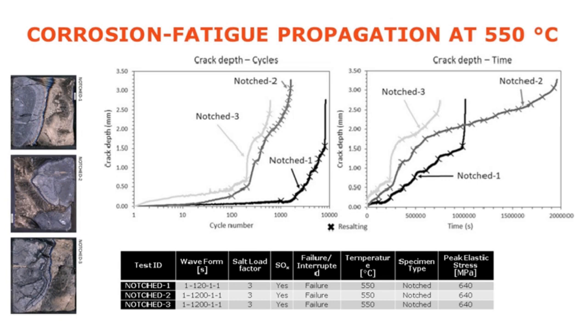We can also see that we get these crack jumps occurring as we resalt the specimen. The crosses on those curves represent the points at which we've resalted the test. As our corrosive species or deposit is used up, it evaporates, or it's consumed in the corrosion process, we have to replenish that. So we can see how the crack jumps and interacts with those resalting processes.